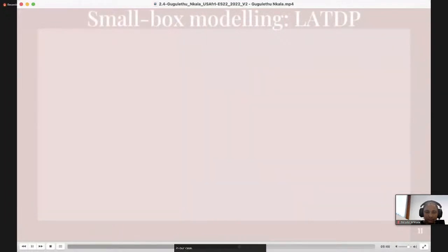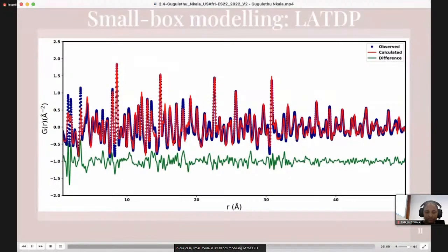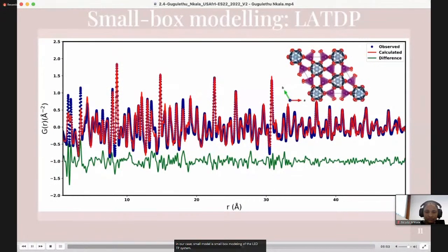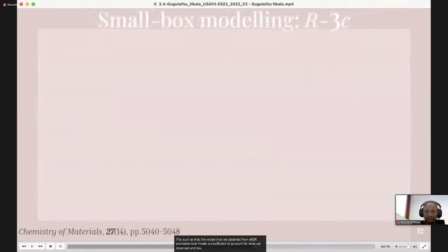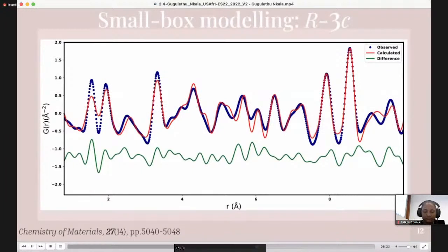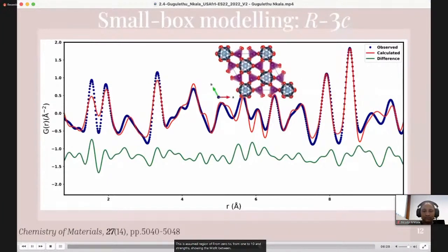In our case, small box modeling of the LATDP system using the rhombohedral structure that we obtained from Bragg data has shown somewhat of a reasonable fit at higher R. But considering the residual, as we go further towards lower R, we notice a greater discrepancy. This suggests that the model that we obtained from XRD, our rhombohedral model, is insufficient to account for what we observe at low R. This is a zoomed region from 1 to 10 angstroms, showing the misfit between our rhombohedral model from X-ray diffraction as well as our experimental data.